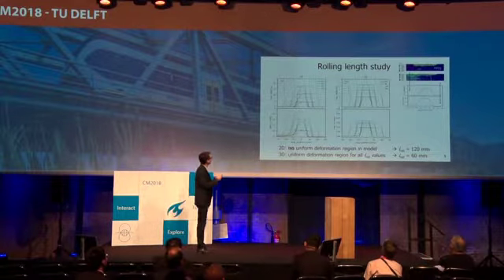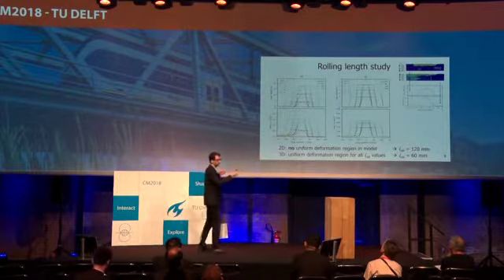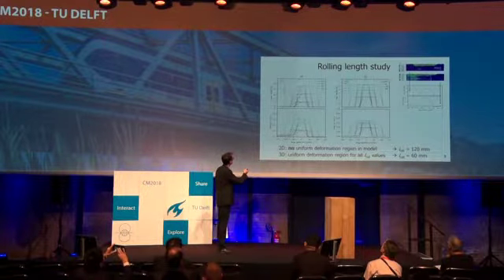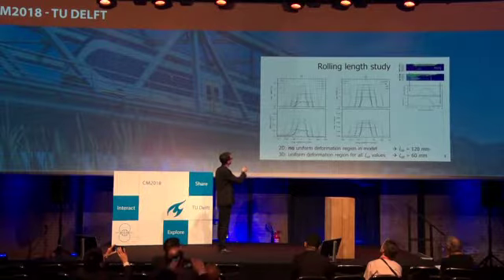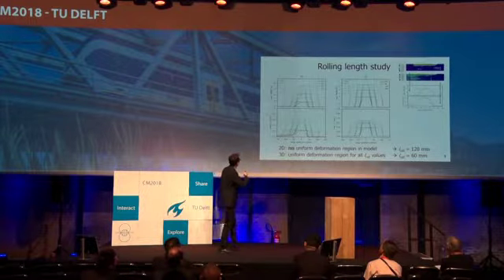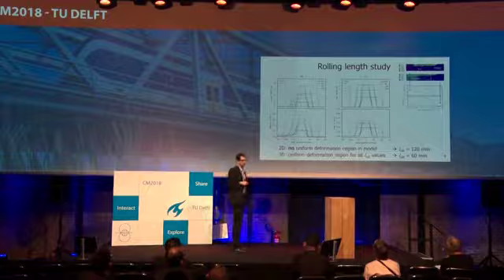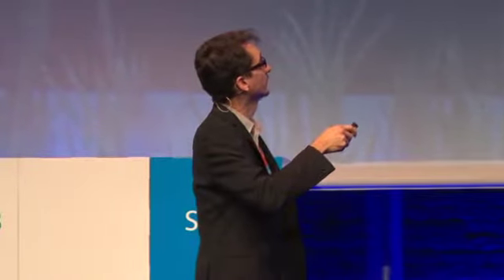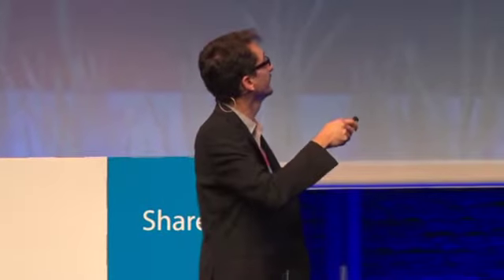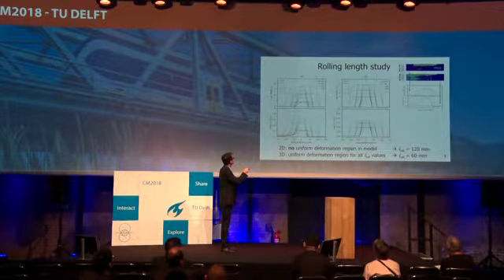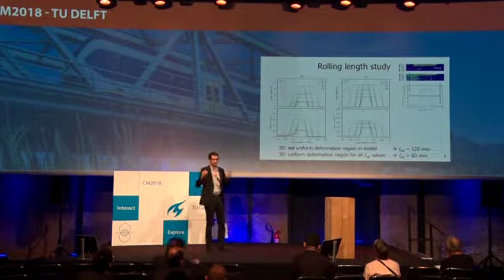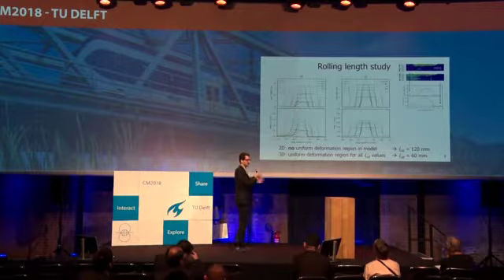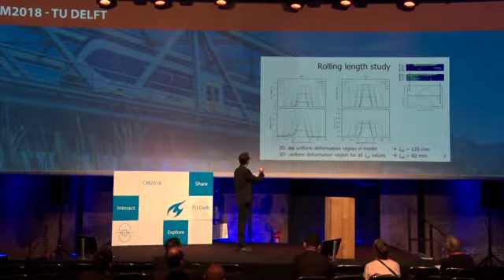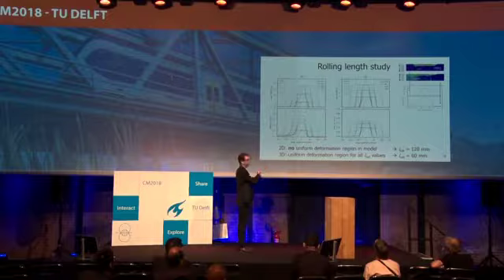Here you see many curves. The wider curves are the ones with a very long rolling length. And this is with 60 millimeters, 60, I think 120 and 200, something like that. We see it here, sure. And those curves that lie above each other, but have different line styles, those are 5 cycles of loading. So we see with more cycles of loading that in the 2D model, this is all 2D, we do not get very uniform plastic deformations over the length. So in 2D, whatever happens before and after it always influences it. The same with the shear displacements here. We see it depends on the rolling length, and the bigger the rolling length gaps, the bigger the shear displacements are.